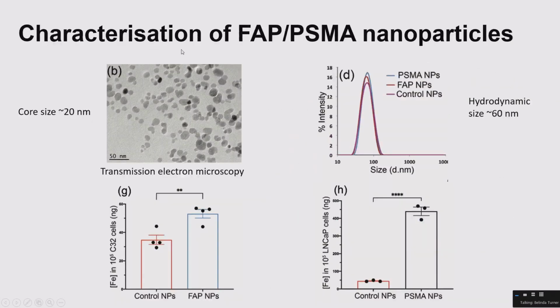So here's just a bit of characterization of the FAP and PSMA nanoparticles. This image here is a TEM image of the iron oxide nanoparticles. So you can see they roughly have a core size of about 20 nanometers, and then here's a DLS image of the hydrodynamic size, which is approximately 60 nanometers.